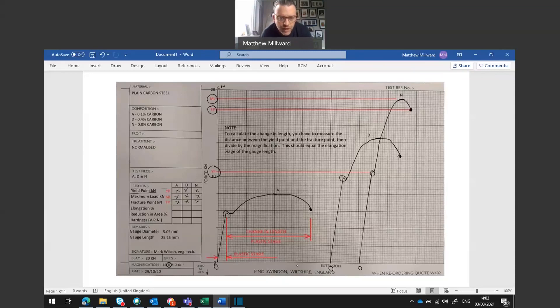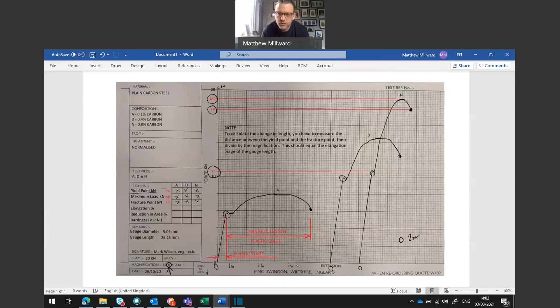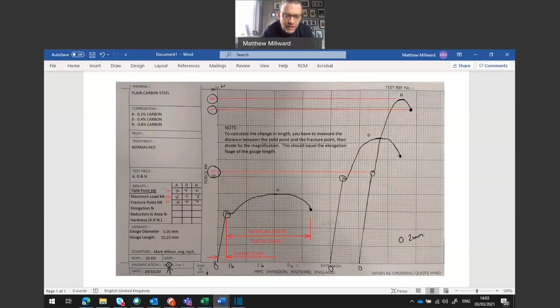The elongation can be obtained from the elongation gauge in the photographs, but we can also work it out from the change in length on the graph. There is a magnification factor: this graph paper uses magnification size 8 and each one of these boxes is 0.2 millimeters. For sample N, the change in length is between the start and end points — count the number of boxes across, multiply by 0.2, and that gives you the change in length, which relates back to the elongation percentage. It should tie in to the elongation gauge within a couple of percent, so you can put in the elongation percentage in each one of these boxes.